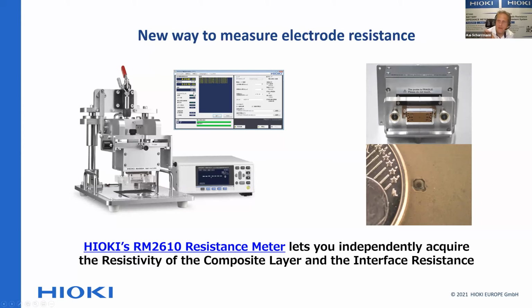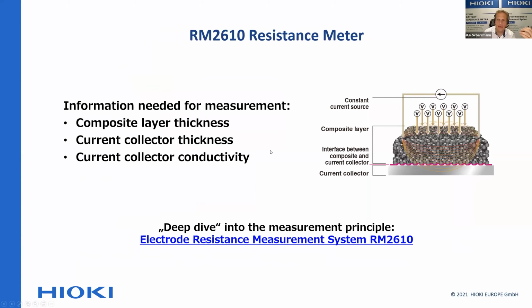These multiple probe tips allow you to make multiple measurements and then put them into a 3-dimensional mathematical model and do a calculation. The outcome is the value for the interface resistance and the value for the composite resistivity, so it is possible to get separate values for that. You only need three pieces of information to feed into the system: the composite layer thickness, the current collector thickness, and the current collector conductivity.